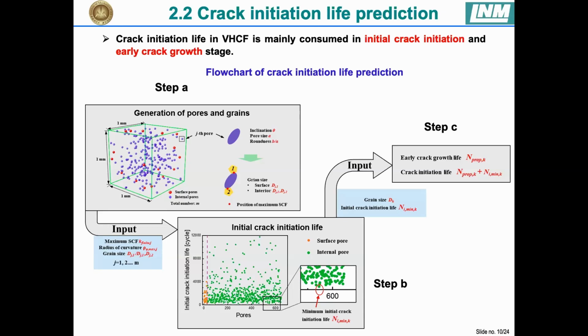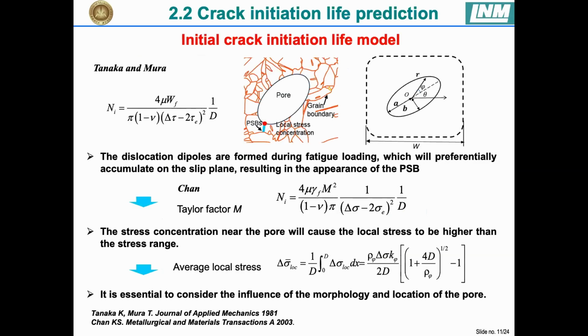The following is the flowchart of the crack initial life prediction model in this study. Step A is the generation of pores and grains in a cell according to the previous microstructure and defect characterization. Step B is calculating the initial crack initial life of all pores, and then the minimum initial crack initial life serves as the critical defect, and the corresponding grain size serves as the input to step C to predict the early crack growth life and the crack initial life. As for the initial crack initial life models, we adopt Chan's model, modified with Tanaka and Mura's dislocation model by introducing the Taylor factor to transfer the micro model to a macro model.